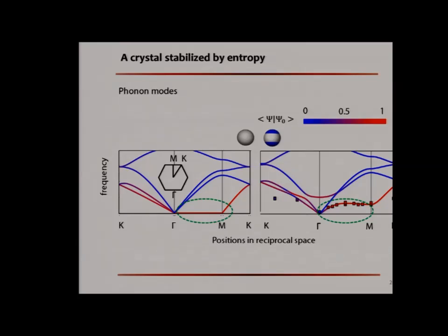For the lattice that is composed of isotropic particles showing on the left, you can see this one energy mode with zero energy, which means there's no energy barrier against lattice deformation. That's why Kagome lattice was traditionally regarded as not stable. But if you look at the phonon spectrum for the lattice made out of our tripolar particles, you can see now that mode has been lifted up. And now we have energy barrier to stabilize our Kagome lattice.